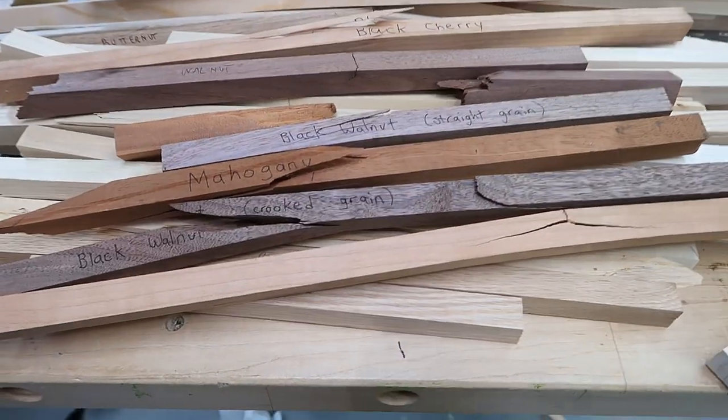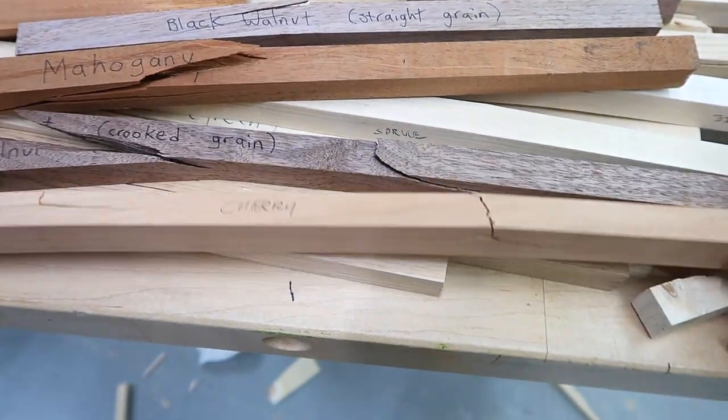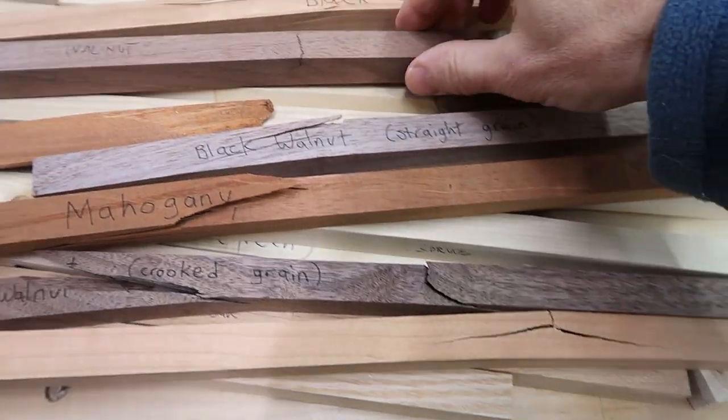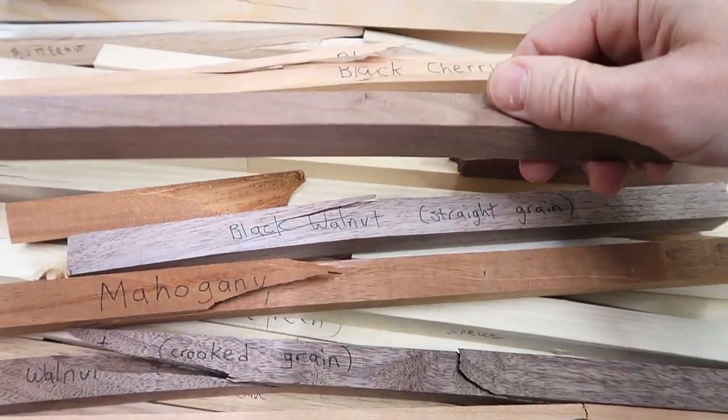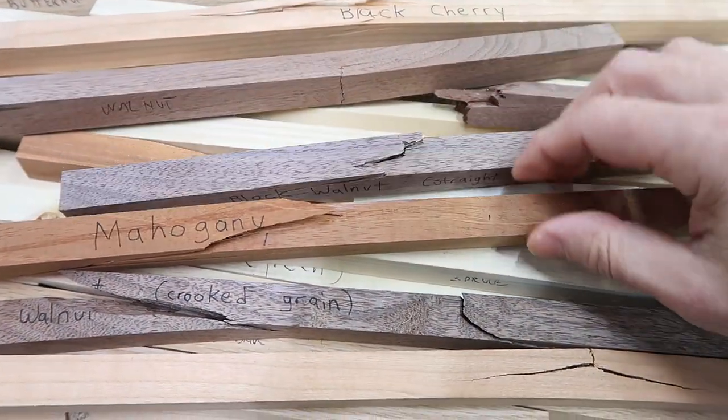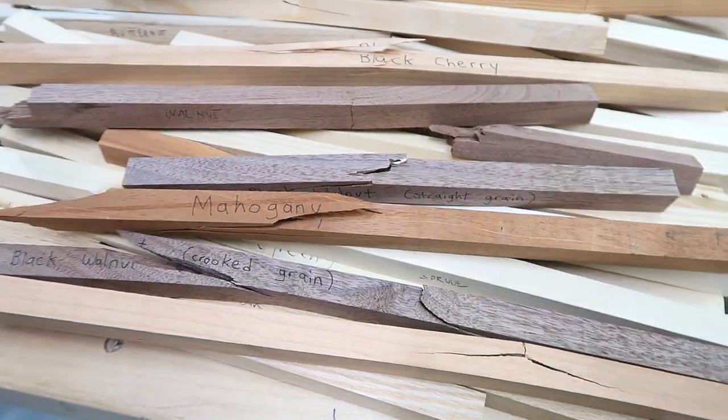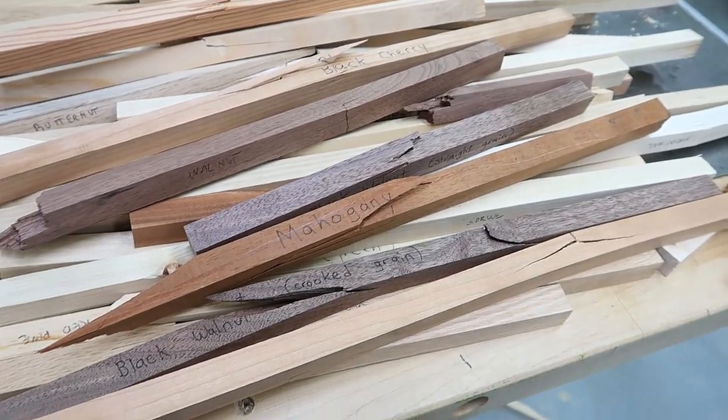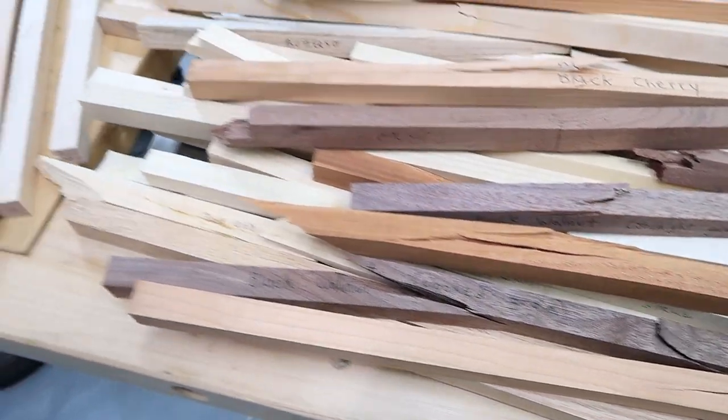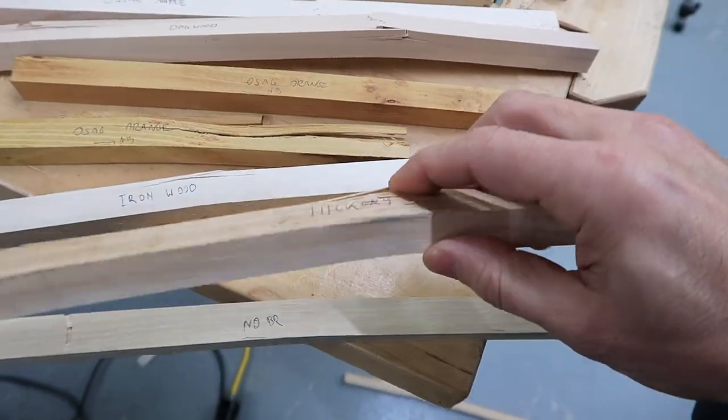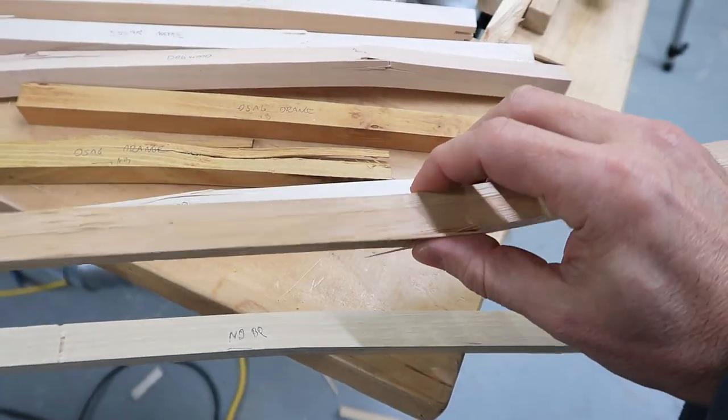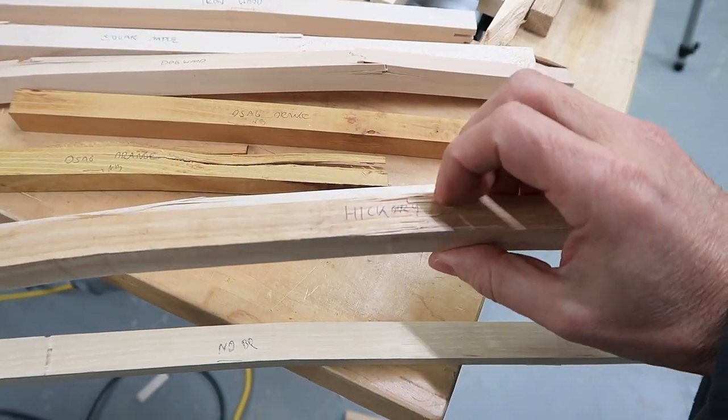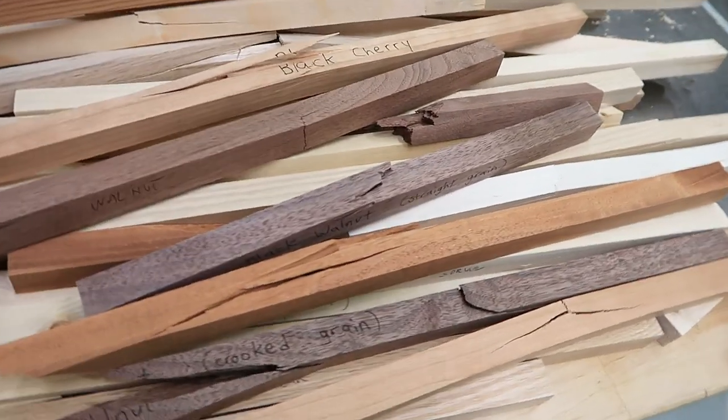Next, the dark woods all seem to kind of fail with a bang, in that they failed all at once without splintering, which is to say they are perhaps a bit more brittle. And to me that says those woods are probably unsuitable for something where strength really matters, like a chair, because you don't want that to just snap in half. It's much better to have something that fails a little bit more gracefully like that, which is to say if you bang it really hard it might crack a little bit, as opposed to just snap in half. So if you want to build chairs that last, don't use dark woods because they shatter too easily. In fact, what makes a good bow wood would probably also make a good chair wood, in that it has a lot of ability to resist breaking when you knock it over and stuff like that. Very important if you have kids.